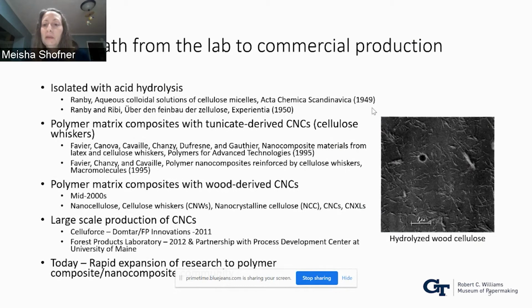It took a while for people to think about using them. One place that people did start to use them, which is aligned with the sort of research we do in my group, is in composites. Basically taking the nanocrystals and incorporating them into a polymer, which we call the matrix. This is a continuous polymer phase with nanocrystals interspersed in there. One of the first groups to do this was based out of France, and they did their work in the mid-90s, looking at water-based polymers, like a paint material, and incorporating tunicate cellulose whiskers, so these materials that came from the sea creature.